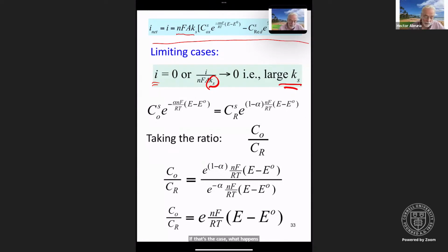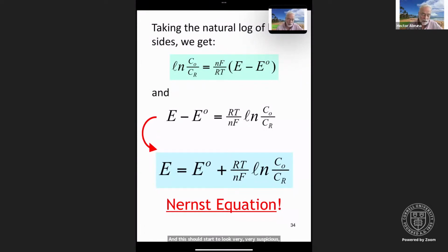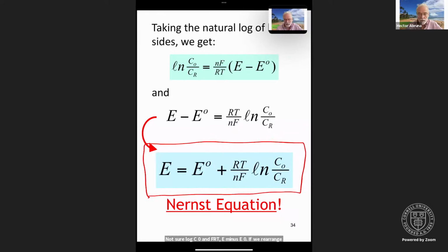If i net equals 0, that means that we can equate both sides, the cathodic and the anodic. We can take the ratio of Ox and Red. So we have C_ox over C_red equals e to the 1 minus alpha, e to the minus alpha nF over RT, E minus E0. We can cancel the alpha, so we end up with C_O over C_R equals e to the nF over RT, E minus E0. And this should start to look very, very suspicious, right? And in fact, if we take the natural log of both sides, natural log C_O over C_R equals nF over RT, E minus E0. If we rearrange this, we get the Nernst equation, okay? Which is a kinetic derivation of what's fundamentally an equilibrium expression.